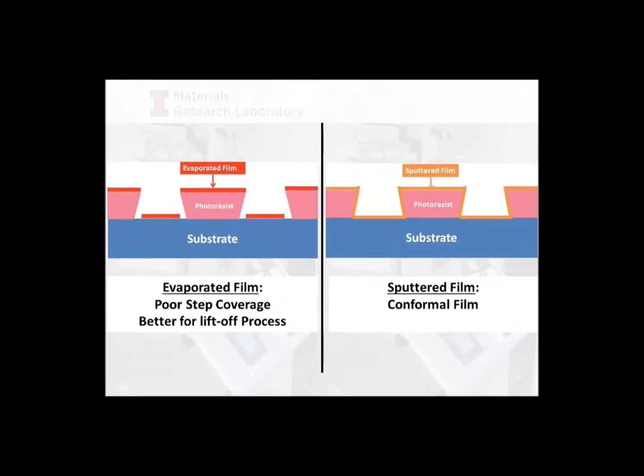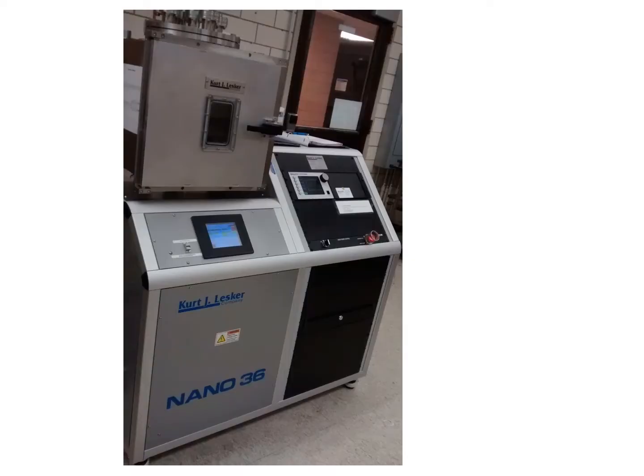Unlike sputtering, thermal evaporation cannot form conformal films. It makes the deposition much more directed, and the side walls of the patterns are not or less coated. So thermal evaporation is an excellent choice for wafers that require a lift-off process.